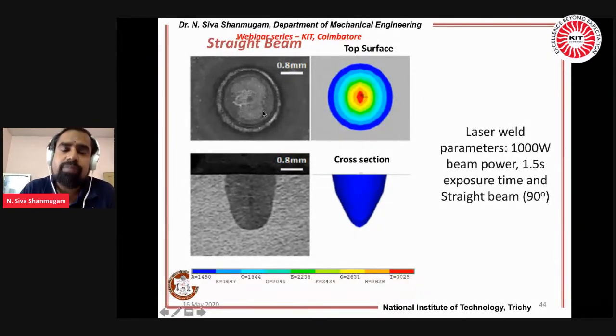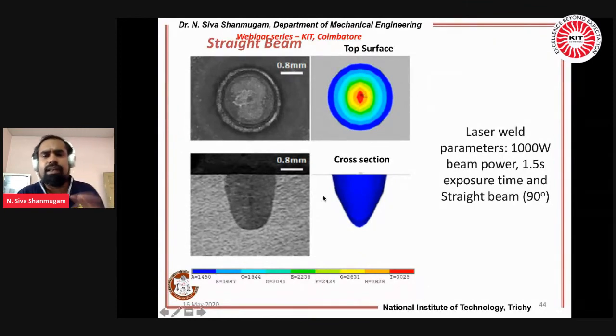And why? Because whenever you want to see the capability of the system, you have to damage something and you have to enrich your knowledge. Without failure, it is very difficult to get fruitful results. So we failed, but we have published in a very good journal. That is the thing I have to focus on here. So this is the top surface, and this is along the thickness direction. These two things are validated. The simulation was validated with the experiment, and the percentage of error is around 1.2 to 1.3%.